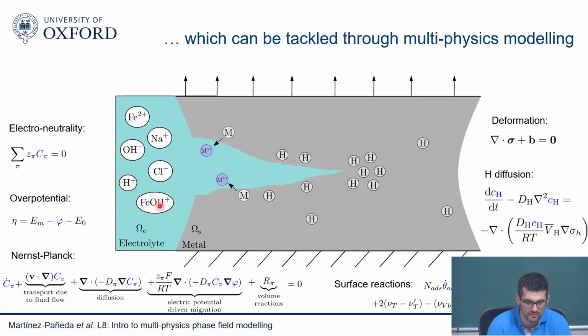So models can be a bit big, but you can see the change in time as a function of transport due to fluid flow, diffusion, electromigration, and volume reactions. These are well known, and they rely on parameters that we understand: diffusivity, temperature, Faraday's constant, and so forth. So everything is physically based, mesoscale physically based. You're explicitly resolving the phenomena at play. And then you have some surface reactions as well, the formation of the material, hydrogen transport, whatever you need.